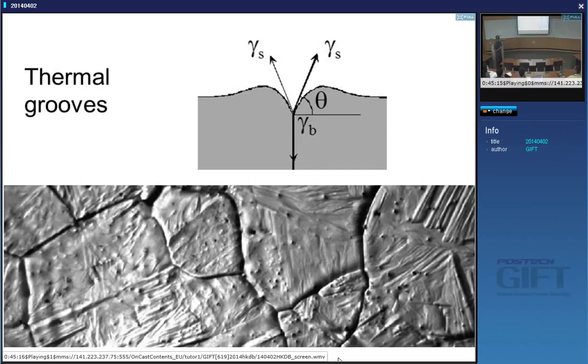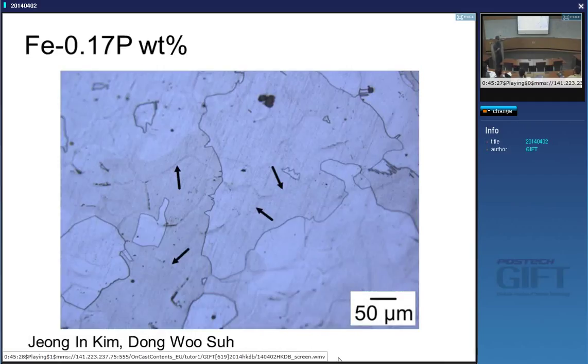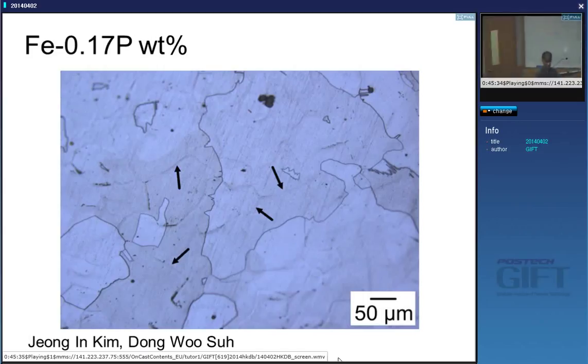If I lightly polish and then lightly etch, the result is that the dark regions are the etched ferrite grain boundaries. The regions not attacked by the etchant have no boundaries — the ferrite has grown across. The grooves are not eliminated because it's only lightly polished, and you can see all the austenite grain positions. It's a beautiful image.